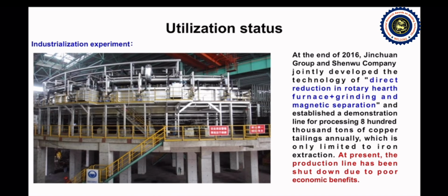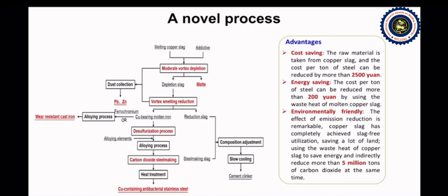At present, the use of copper slag in the world mainly focuses on iron extraction, but the coexistence of copper and iron has caused great technical difficulties for its comprehensive utilization. Therefore, a new process of copper slag treatment is proposed. The specific approach is that after moderate depletion of molten copper slag, copper metal and depleted slag are obtained. Then, the depleted slag is reduced by vortex melting reduction to obtain copper-bearing molten iron. Copper-containing molten iron is alloyed, tempered, and heat-treated to obtain wear-resistant cast iron or copper-containing antibacterial stainless steel.